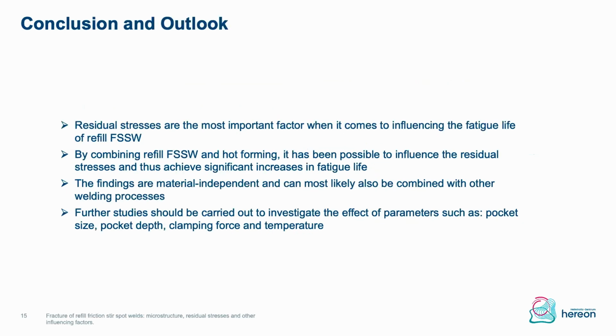So the conclusion is that residual stresses are the most important factor when it comes to influencing the fatigue life of refill friction stir spot welds. By combining refill friction stir spot welding and hot forming, it was possible to influence the residual stresses, and thus achieve a significant increase in fatigue life. And these findings are material independent and can most likely also be combined with other welding processes. Further studies should be carried out to investigate the effects of pocket size, pocket depth, clamping force, and also the temperature.